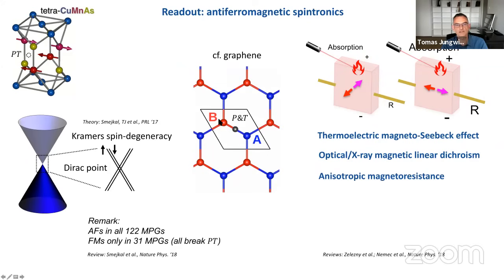We are familiar with these Dirac points from graphene, and I'd like to emphasize that in graphene, the Kramers degeneracy is because there is both individual parity symmetry and the time reversal symmetry. That is not present in this antiferromagnet. It only has the combined symmetry, but that's enough for having the Kramers degeneracy. I'd like also to make a remark that this is only possible in antiferromagnets, while in ferromagnets, you cannot have systems which would have this combined PT symmetry. So the Dirac points are in principle only allowed in antiferromagnets.